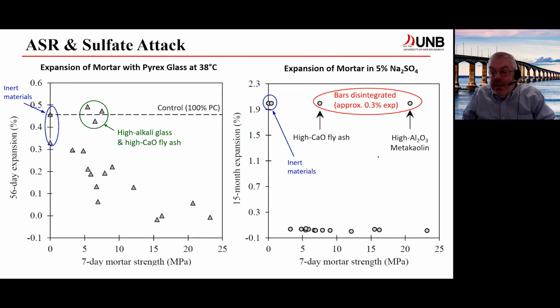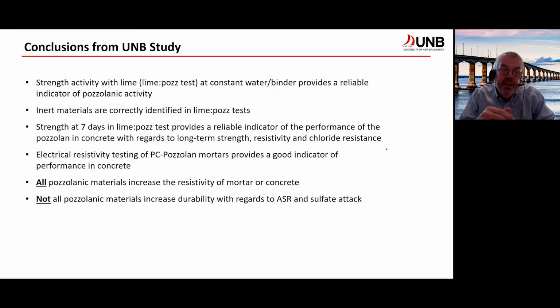But when they're used at relatively low replacement levels, like 10 or 15%, they're not going to help with sulfate attack because the alumina is contributing towards the amount of ettringite that we form. So we might not necessarily get an improvement in performance. So the conclusions from our study are that a strength activity test for lime is a good way to move forward. The other tests, the Rilem tests, are also very useful. We do have, today, good test methods for evaluating pozzolans, whether they're new materials or existing materials. I think our increased use of these materials relies on us being able to properly evaluate them.